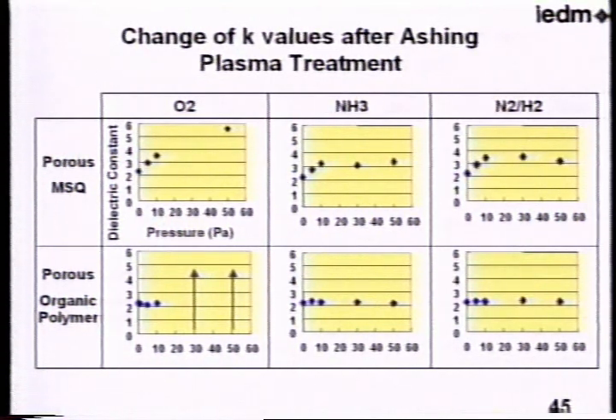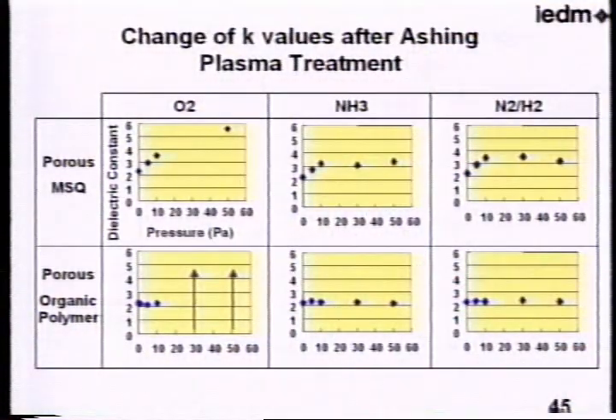So we are investigating several kinds of etching gas against the porous MSQ and porous organic polymers. If we use oxygen, it's very bad, much increase in the K value, and also in the case of organic polymer. If we change the gas into ammonia and nitrogen and hydrogen, the situation is much improved, but still some increase in K values for porous MSQ. Thus, we should improve this kind of etching technology more to reduce this kind of K value change. This kind of work has been done recently.